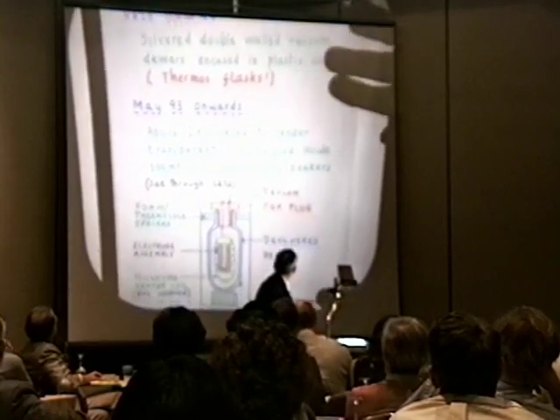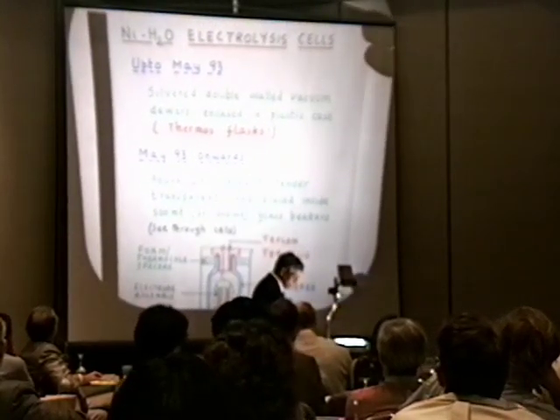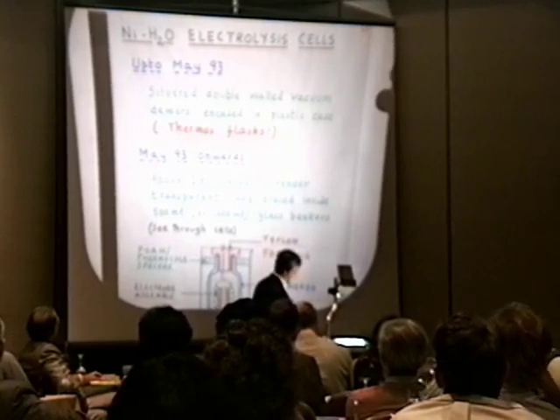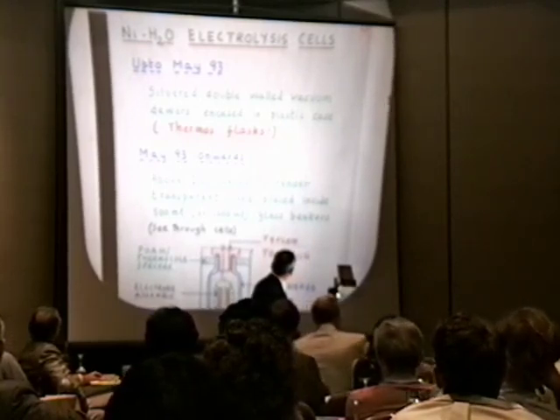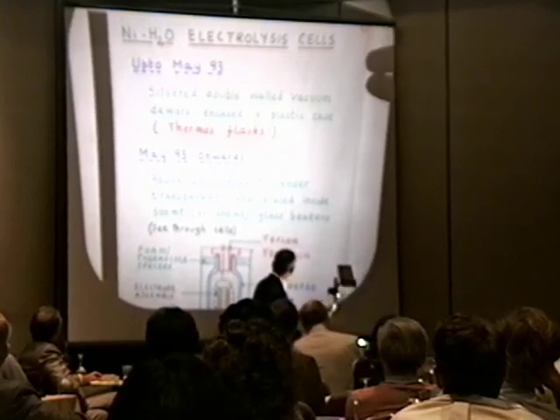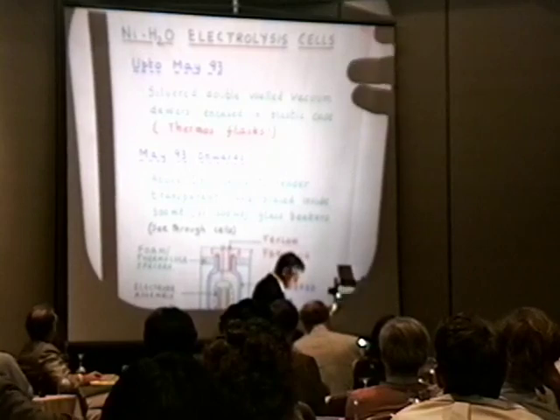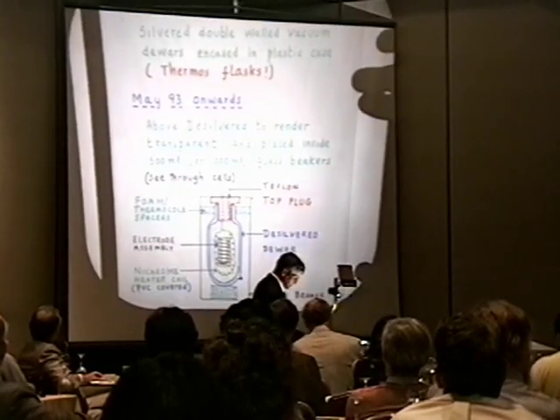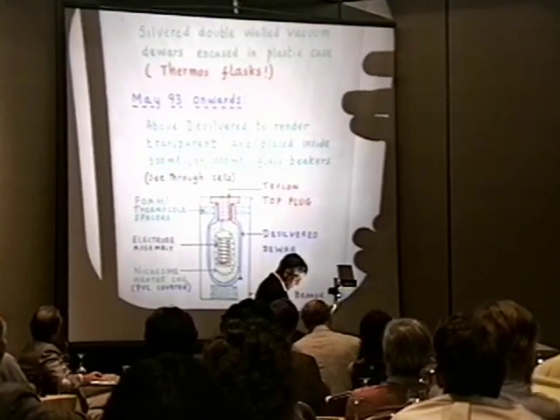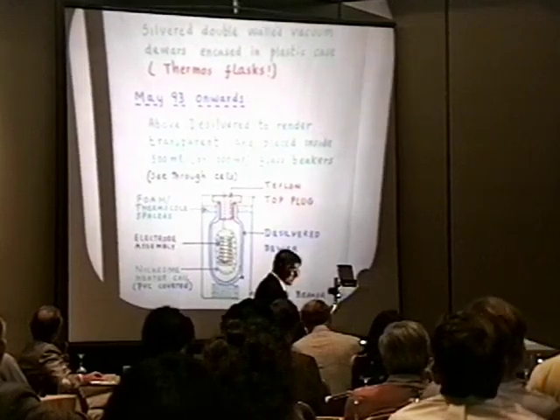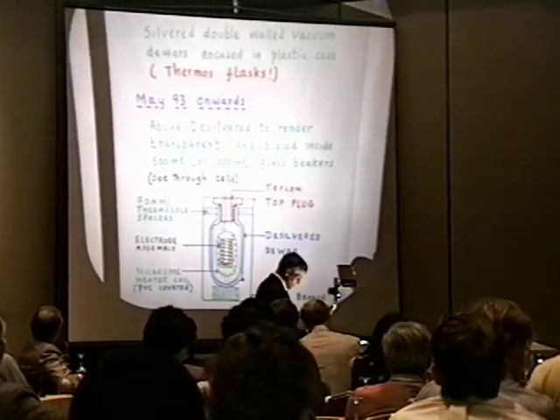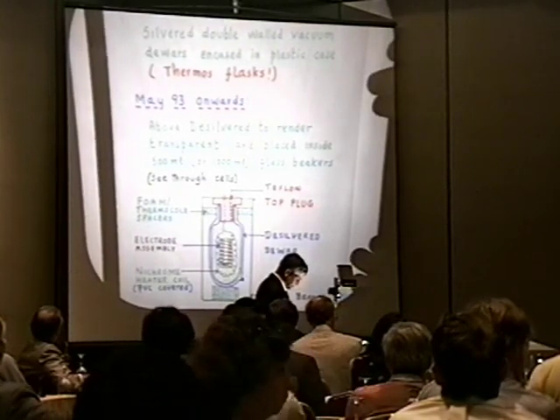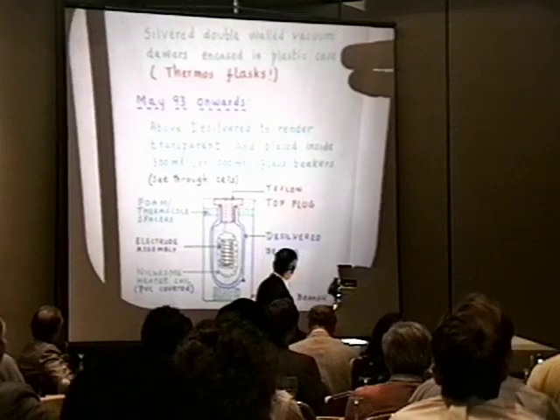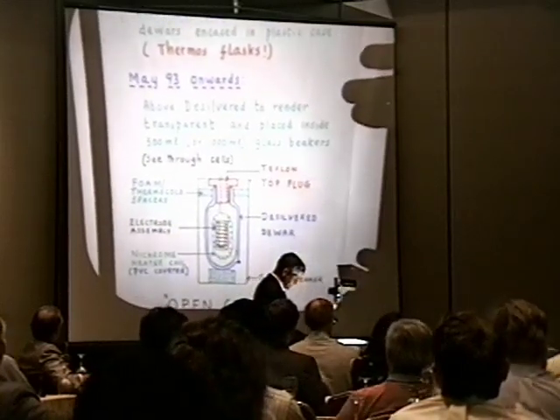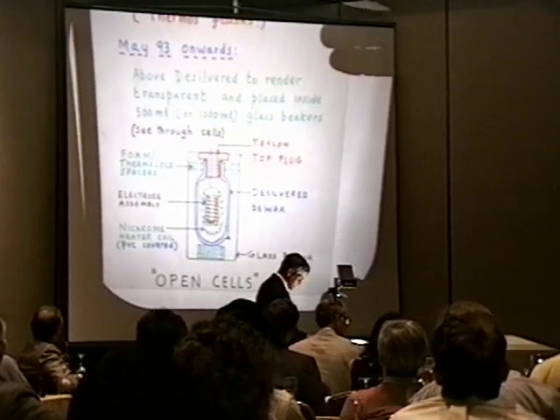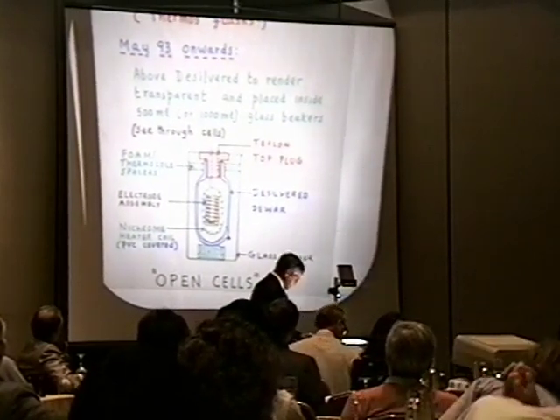The cells. Up to the month of May 93, we used silvered double-walled vacuum vessels, essentially commercial thermos flasks, which I described at the Nagoya meeting. Since May 93, the above flasks were desilvered by breaking the vacuum between the two double walls, because we wanted to get a transparent cell and also be able to go on to slightly higher power. So we had to purposely reduce the sensitivity of the system. This is a diagram of what I call the see-through cells.